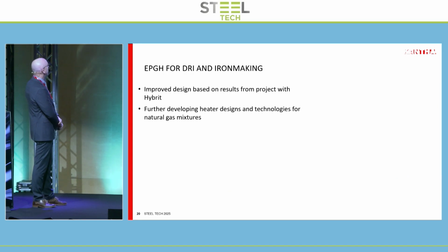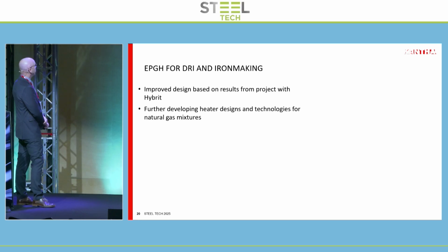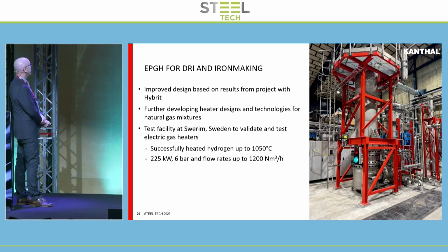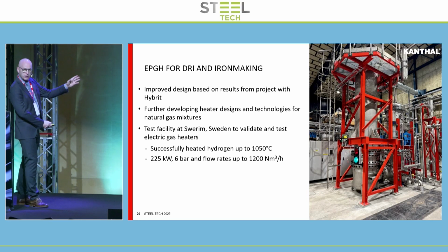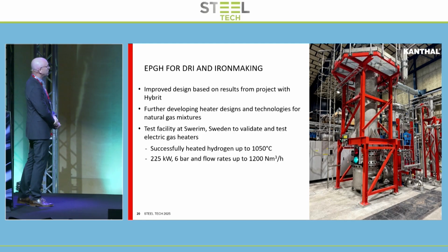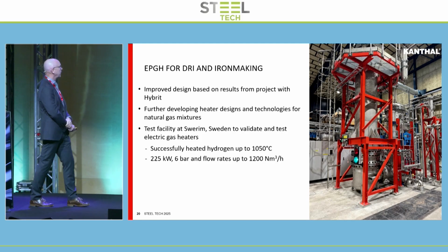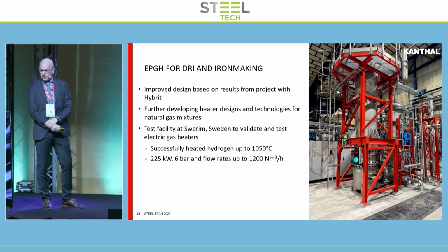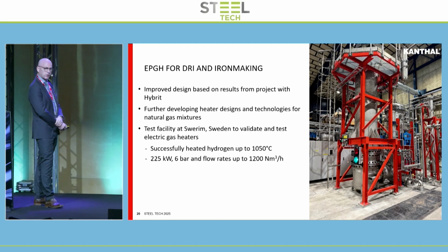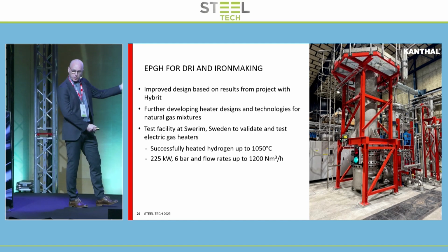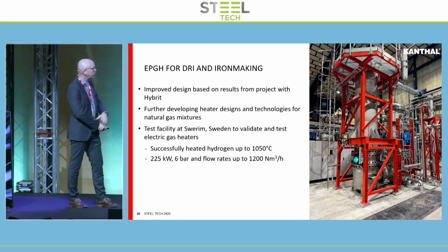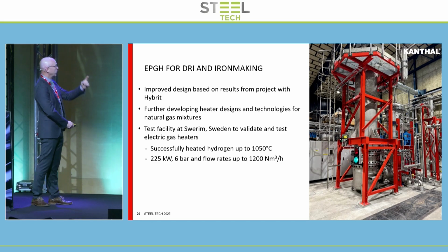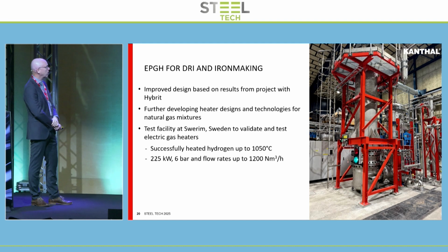Just some comments on further development. I talked about this being an offspring from hybrid. We're working on further development with Danieli on that. We have a test facility also at Swerim in Luleå, as you can see in the picture here. We successfully heated hydrogen up to about 1050 degrees centigrade at 6 bar. It's a rather small system compared to what we endeavored to build here, 225 kilowatts, but we have a recirculation system and we can test our development of our heating technology.